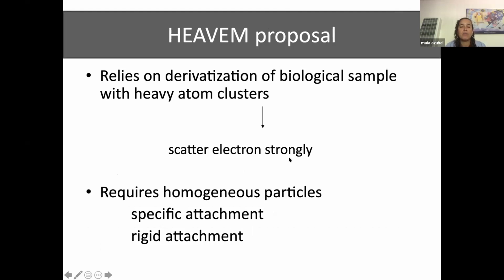And the idea was that we need to find an object that can be easily imaged under the transmission electron microscope when you collect the images close to focus, so you don't lose the high resolution information. And for that, you can use heavy atom clusters. We ended up working with gold nanoparticles because gold is a very good metal to combine with biological samples.